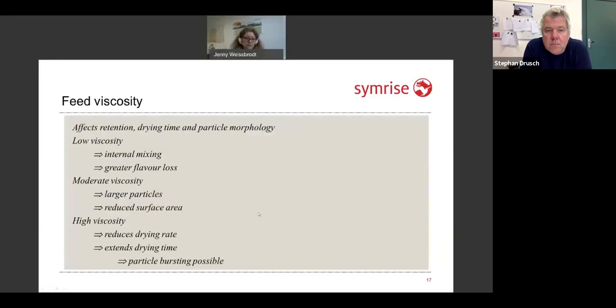Coming to the feed viscosity. The feed viscosity directly affects the retention, the drying time, and the particle morphology. If you have a very low viscosity, you have a very high degree of internal mixing. The movement within your drying droplet is very active. The kinetic energy is high as the particle heats up, and the molecules are just moving around. And even the oil droplet is moving around a lot, and this means during time of drying, the oil droplets are transported to a greater extent to the surface of your particle, where your active can be lost.